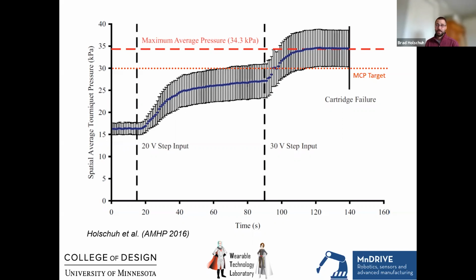One of the downsides to these materials, which we'll talk about on the coming slides, and I acknowledge this fully, is that these materials produce actuation as they go through phase transformation. They go through phase transformation when they get hot. Now, hot is a relative term. There are several flavors of these alloys with different material compositions and different temperature transition windows. But when you're dealing with actuators of this form, you have to keep them hot in order to keep them stiff. As soon as their temperature drops, either because you've turned off the electricity that's heating it or because they've acclimated to ambient temperature, so too will the force and the stiffness drop off. So in order to achieve pressures like this, they have to be continuously powered, which is not ideal.